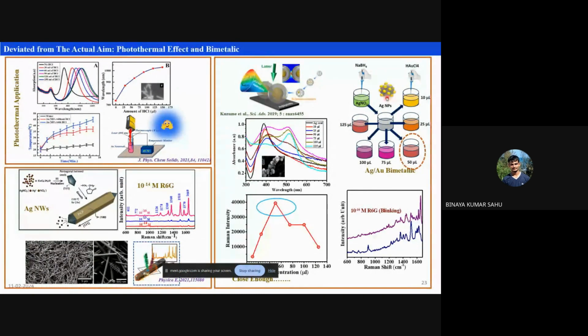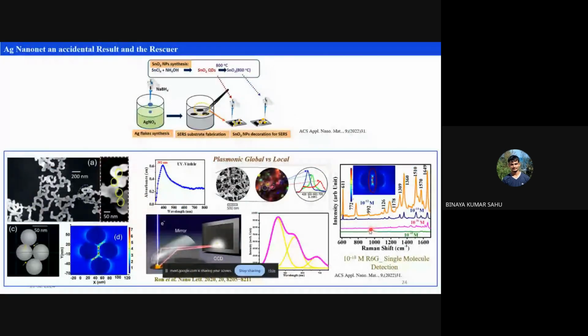And this is a beautiful structure that we prepared by varying the concentration of silver. Here we could go up to 10 to the power minus 16. So earlier we could go up to 10 to the minus 11, then it improved to 10 to the minus 14. Now we are dealing with 10 to the minus 16. But our mark was 10 to the minus 17. If I could detect up to 10 to the minus 17 rhodamine 6G, then I can go for my real experiment. And this thing happened.